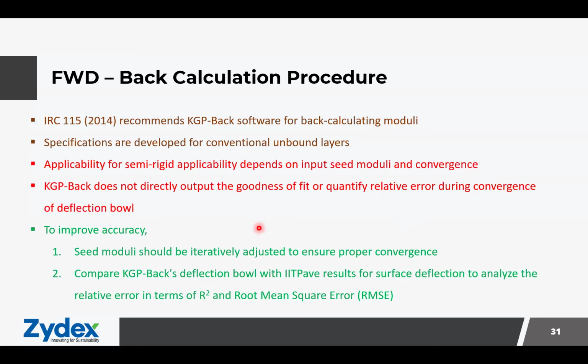This issue can be addressed by giving a seed moduli and iteratively changing the seed moduli to ensure proper convergence, or else by comparing the KGP back's deflection bowl with IIT PAVE. That means the modulus that we have calculated from KGP back can be put into IIT PAVE, and then we find out the surface deflection corresponding to the offsets that we have considered. By comparing the two deflection bowls, we can measure the relative error in terms of the root mean square error.